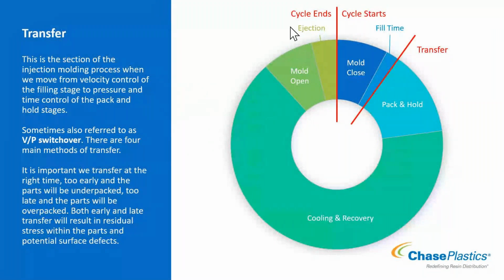Okay, so once we've filled the tool to our 95 to 98 percent, we transfer from velocity control to pressure control. Many people call this transfer. Others will know this as the VP switchover position. That VP literally means velocity to pressure switch position. So we're switching our control methodology between fill and pack and hold.